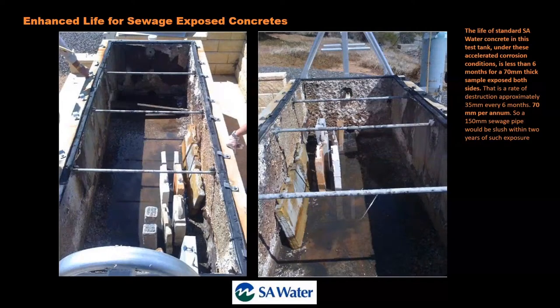This is an actual project that was carried out by South Australian Water. They built an environmental test tank where they divert raw sewage through this test tank. You can see the rubber seal on the top. They put a lid on it, so it's completely hermetically sealed. They also introduced hydrogen sulfide gas into that end of the chamber to really accelerate things. Normal concrete is put in there, and to pass SA Water's requirements, it needs to lose no more than 70 millimeters per annum. Most concrete, normal concrete and coated concrete, is put in there. It's a very, very destructive process, and very typically this 70 millimeters of concrete is totally destroyed within about 6 months.